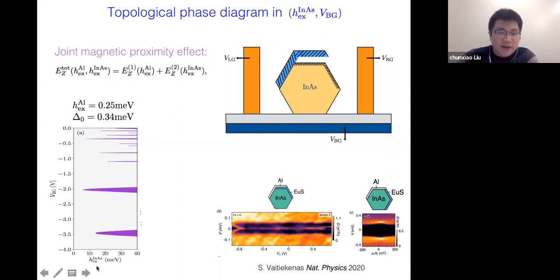So that's how we determine the value of the exchange coupling in aluminum. And okay, so this is the phase diagram. We see that these purple lobes are the topological phase, and the gray area is the trivial phase. Let's focus on these two lobes at more negative backgate. Important information is that the tip of the lobe, which is the minimally required exchange coupling for realizing the topological phase in this ferromagnetic hybrid nanowire, is about, say, 10 meV, which is a reasonable number. So that indicates that for this ferromagnetic hybrid nanowire with an overlapping geometry, it is possible to realize topological superconductivity with realistic parameters.